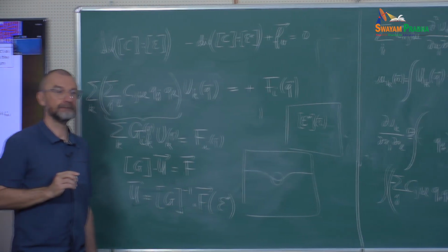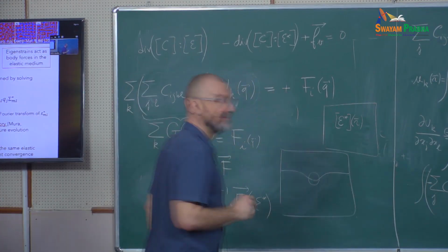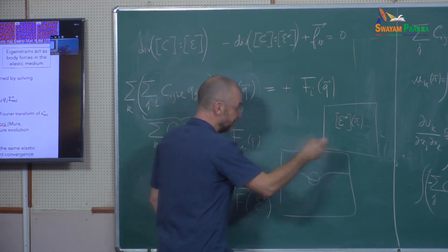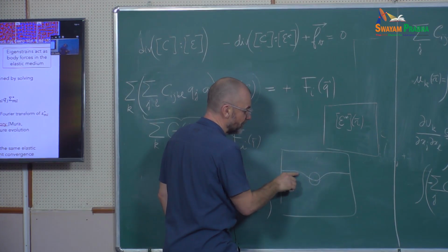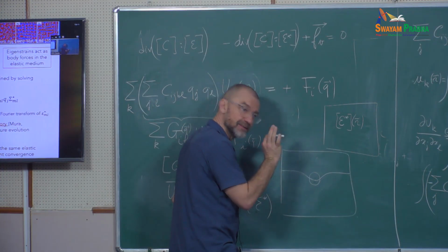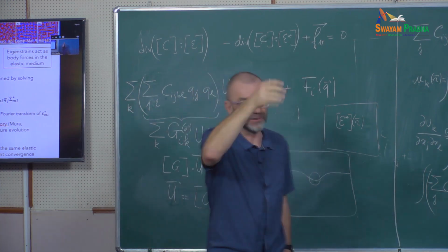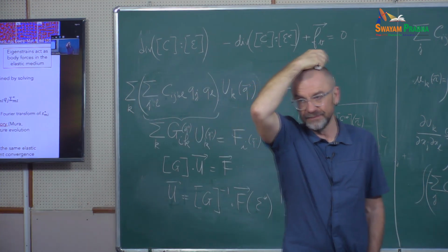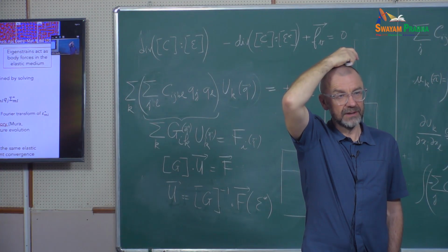For this continuous change, do the precipitates have to be coherent? Yes. I could have put that as another limitation. Because we assume continuity of the mechanical properties at the interface, implicitly we assume that it's a coherent interface. Yeah, good point. Are there other questions at that point?